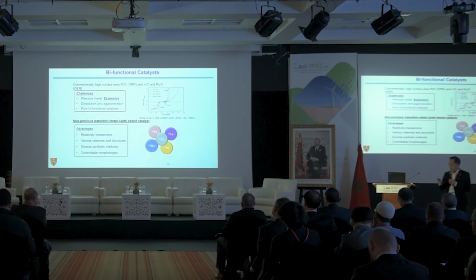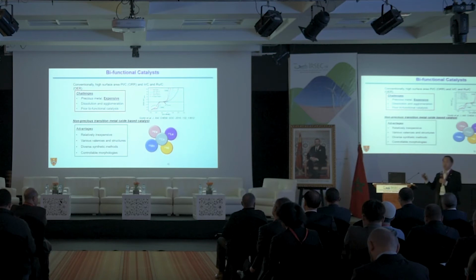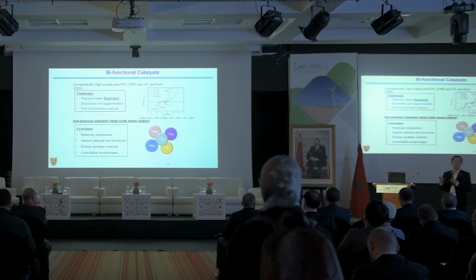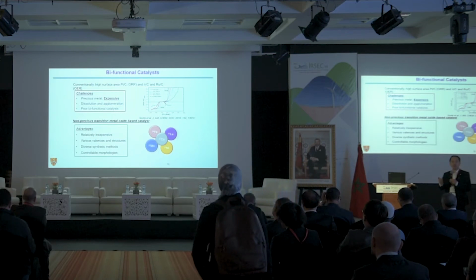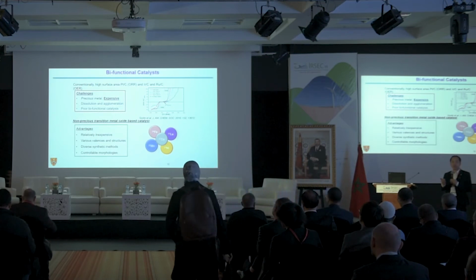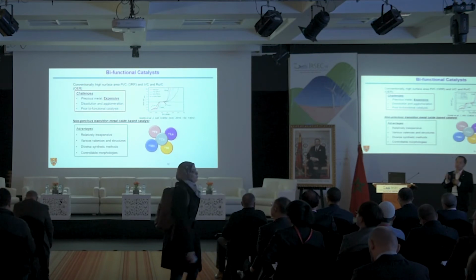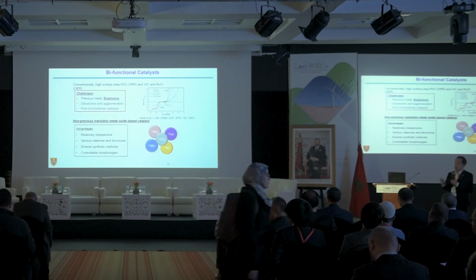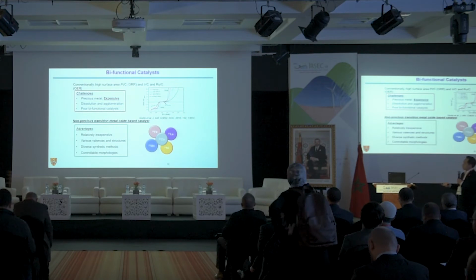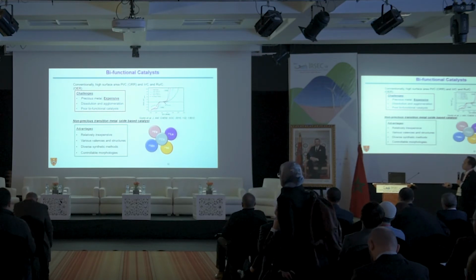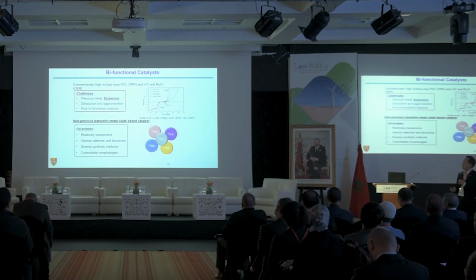So commonly, actually, the precious metal catalysts like platinum or iridium will be suitable for ORR or OER. And typically, they are more stable. However, these are too expensive. If we want to have a low-cost rechargeable zinc battery available for the market, we'd better not use the expensive metals. So in terms of that, we try to use a non-precious transition metal to meet this requirement.